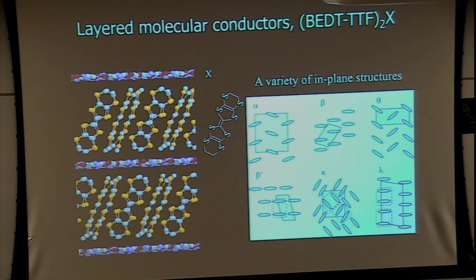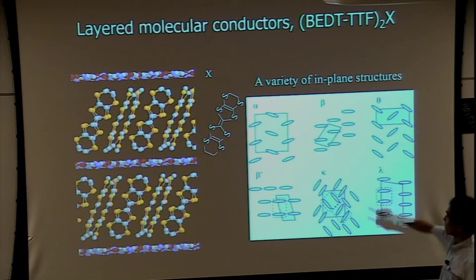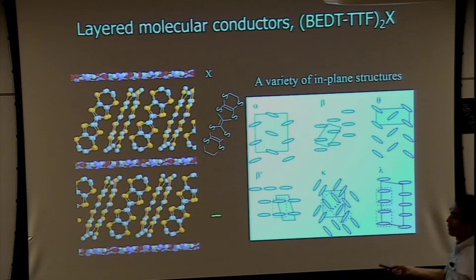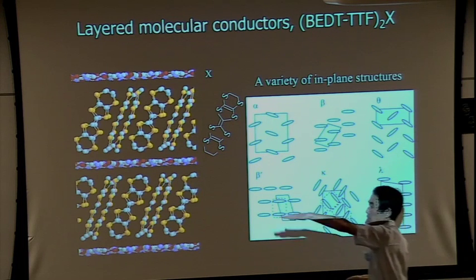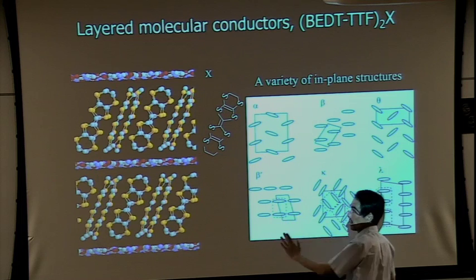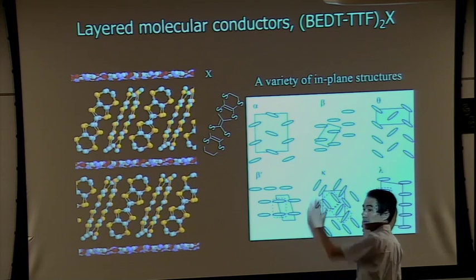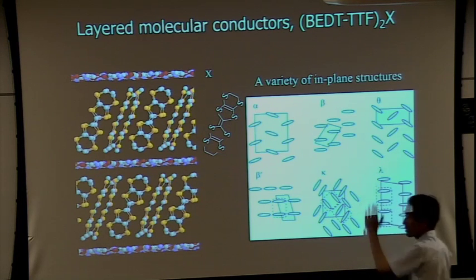But the conductivity ratio is typically 1,000 for all these materials. It's conductive in this layer, in these two-dimensional directions, but in the perpendicular direction it's very bad electric conduction.